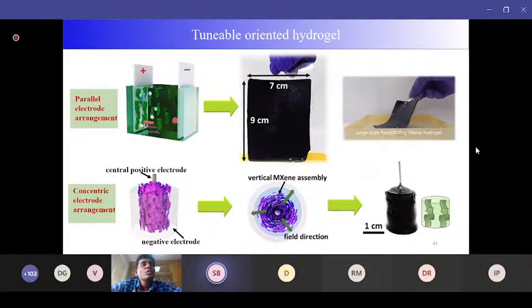And we can control the orientation of the MXene sheets, like parallel orientation. So you control the orientation of the field. If you use positive and negative like this, a parallel configuration, you can get this kind of sheets.